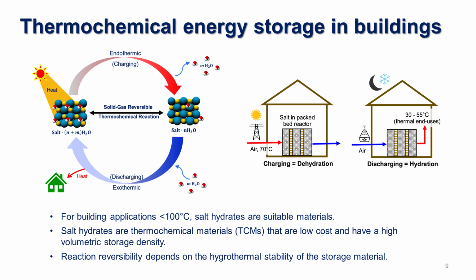So in a realistic system in a house, this is what the charging reaction would look like. We would use either solar energy as heat, or we would use low-cost grid electricity to joule heat our material. And when we joule heat our salt in this packed bed reactor, it's now going to undergo this endothermic charging reaction, and it maintains energy within this salt. And then when we want to extract that energy, we'll introduce moisture, so this relative humidity. And as your salt takes in that moisture, it's going to now undergo the exothermic reaction, which will give you heat at the temperatures that you would want for a building application.